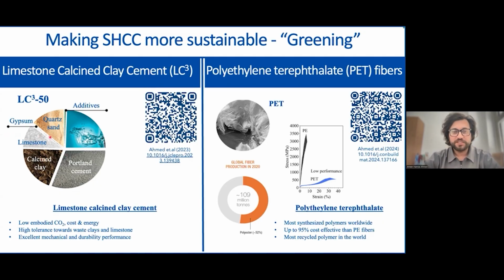For example, the system you see here is called LC3-50. That means it only contains 50% of Portland cement, while the remaining is mainly calcined clay and limestone, and a small amount of gypsum that we add in the binder for proper sulfation. And what is really interesting is that LC3-50 is highly tunable. We don't really need to stick to 50%. We can go even further. In one of the studies linked here by the QR code, we developed many LC3 composites, reducing the clinker content all the way to 25%, meaning the development of LC3-25. And we were still able to achieve a 28-day strength of 25 megapascal with a water to binder ratio of 0.4.